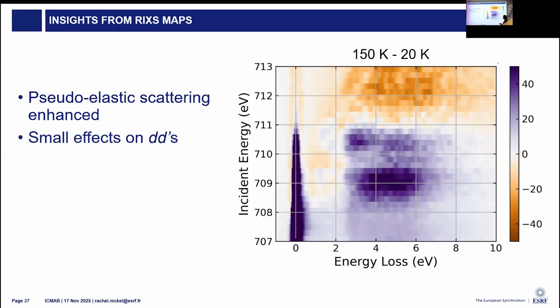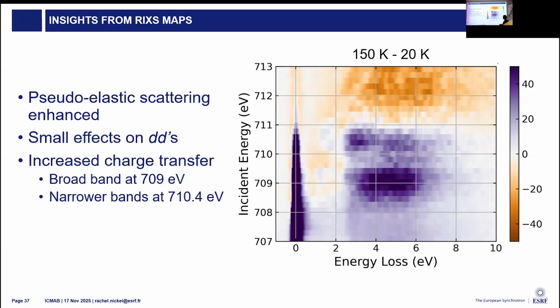We have small effects that show up on the DDs. They're very, very tiny, but there's 2 purple dots here as well as the purple one here where we have slight enhancement. This is consistent with what was measured with neutron scattering, where we don't see a change in structure. So the actual electronic structure, the orbital structure on the iron sites, isn't changing between 20 Kelvin and 150 Kelvin, consistent with what we've measured. What's been measured structurally, I should say.